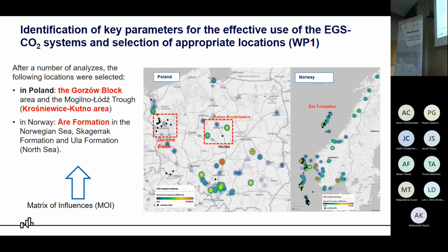As Leszek said in the previous presentation, we chose locations for our survey. We also chose a method for selecting the best location, a matrix of influence, and finally we found two best locations in Poland. The first one is here, the Gorzów block. I can say that it's our first location, and the second location is here. It's onshore, opposite to the Norway selection, because in Norway we find first of all Åre formation, but our Norwegian partners also found two more formations, here in the North Sea, Skagerrak and Ula formation, but first of all, this Åre formation is interesting for us.